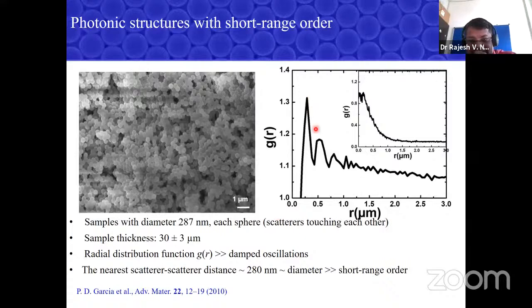And this kind of nice oscillation up to 1.5 micron actually shows there is an ordering, a short range order. And if this sample does not have a short range order, if it is made up of powders like chalk powders in your lab, you take the same picture, do the pair correlation, you don't see any oscillations. You see only decay.